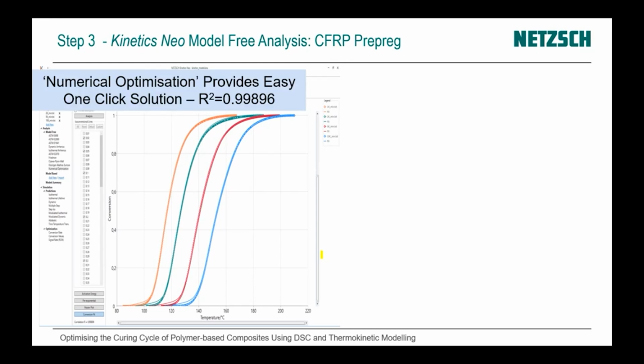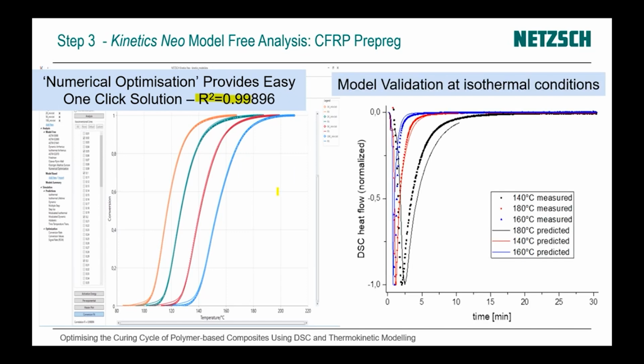In this case, numerical optimization, model-free optimization was done with one click, and the result has a very high value of R square. Then you make a validation of this model, not for dynamic heating as it was for our modeling, but for isothermal data. And we see that for isothermal data, the difference is, in the worst case, less than half a minute. So we can use this model.